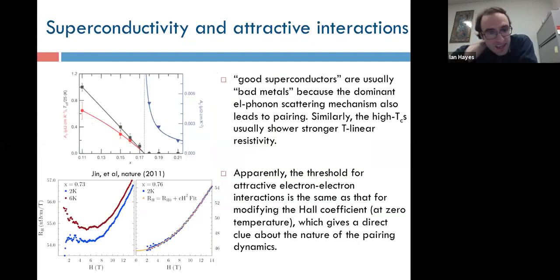The final thing I'd like to say about these results is that they provide potentially more information about the structure of the interaction that is responsible for superconductivity. So there's been a lot of work correlating the T-linear term in the resistivity with Tc, and that's been seen in a lot of materials, cuprates as well as pnictides. The analogy being that the stronger the scattering is, the stronger the interaction is, and therefore the stronger the attractive part of the interaction will be. The resistivity by itself doesn't allow you to factor out which part of the interaction will be attractive ultimately at low temperatures.